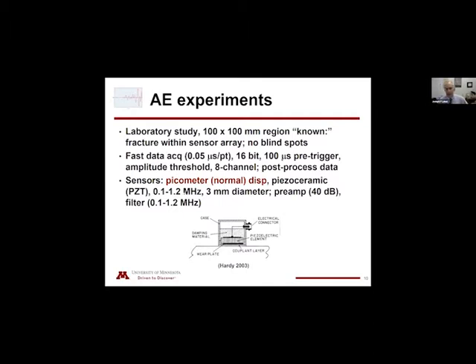I mentioned the frequency content. Because of this high frequency, typically the sensors are quite small, which has advantages, of course, in terms of location, considering a point sensor. These signals, because they're very small, are amplified prior to recording, and to reduce the noise, a filter is typically included.